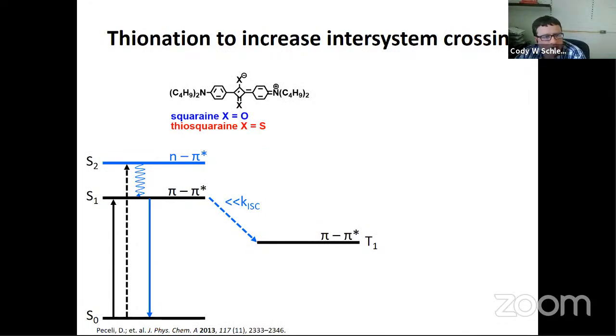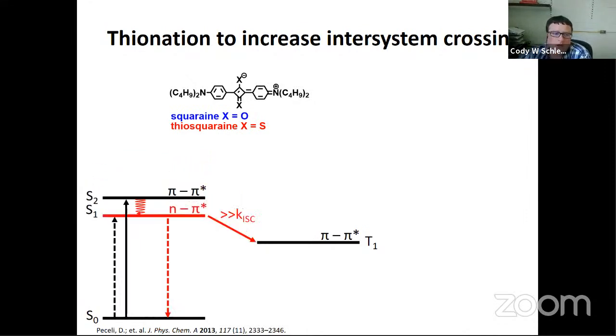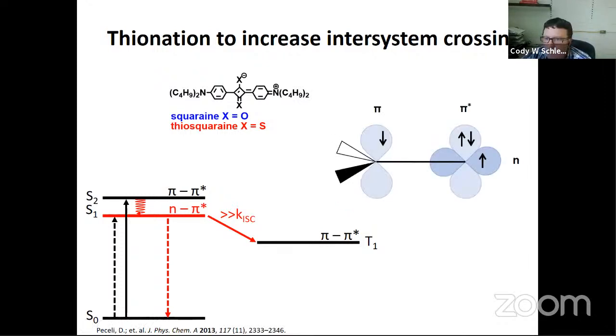So what's El-Sayed's rule? El-Sayed's rule basically says, hey, if I introduce some non-bonding orbitals below my bright state of my absorbing molecule here, I've now got this state, which is an n to pi star non-bonding orbital excitation that hangs around and just waits for something to happen. It doesn't emit very strongly. And if I've got a triplet state that I can intersystem cross to, I can undergo spin orbit coupling based on the coupling of that n to pi star, the triplet pi to pi star state, essentially looking something like this. And so this orbital energy alignment of n to pi star and pi to pi star for singlets and triplets introduces some spin orbit coupling character, and that's El-Sayed's rule. So that's essentially what we've taken advantage of here.